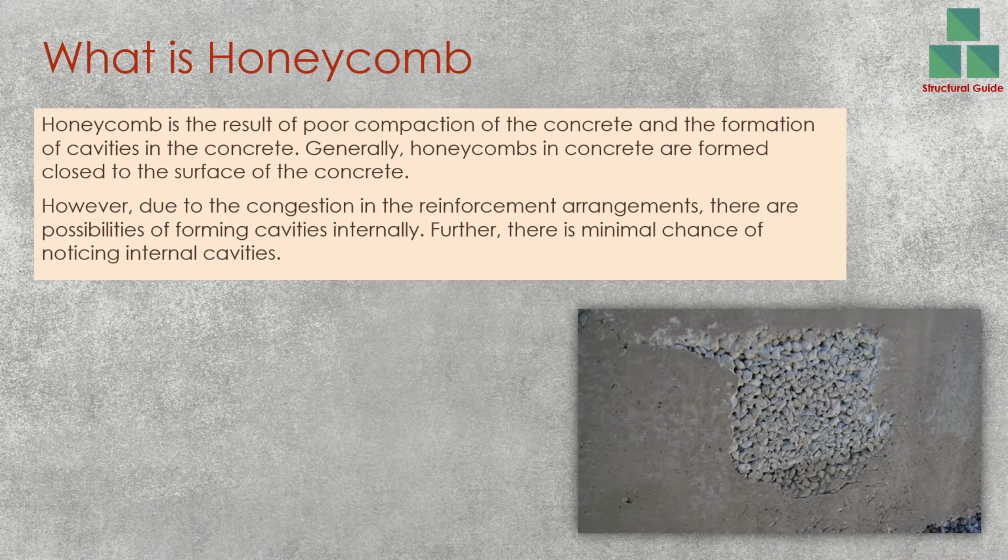What is a honeycomb? Honeycomb is the result of poor compaction of the concrete and the formation of cavities in the concrete. Generally, honeycombs in the concrete are formed close to the surface of the concrete, but there are chances or situations where internal cavities are formed due to the heavy congestion of the reinforcement and due to the inadequate compaction of the concrete.